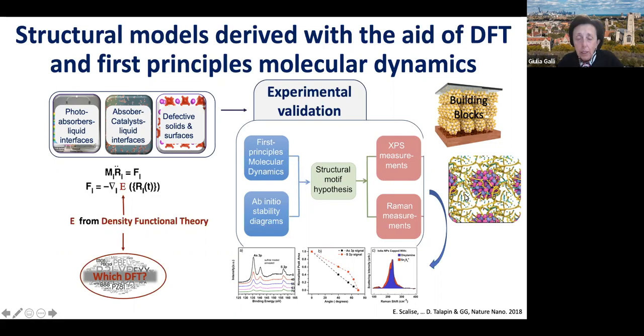So here we did several first principle molecular dynamics simulations to just identify structural motifs. And then for these structural motifs, we identified the signature that you would have if you did XPS and Raman measurements. And our collaborator, Dmitri Talapin at the University of Chicago, did measurements on that, and we went back and forth until we had structural motifs that actually resembled experiments, and this was our starting point.